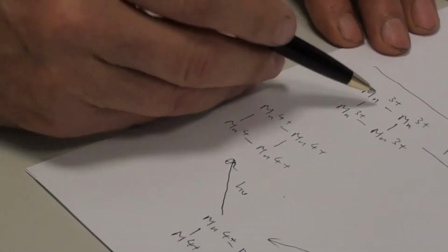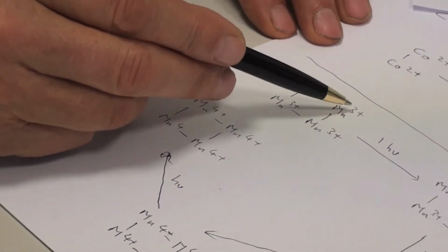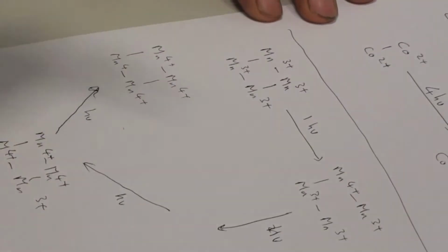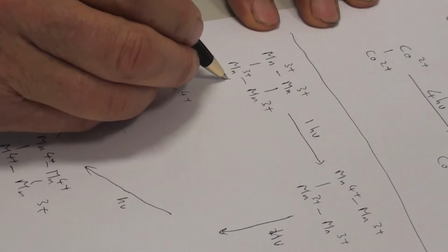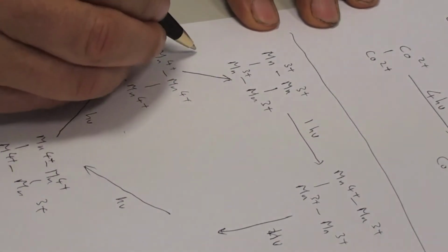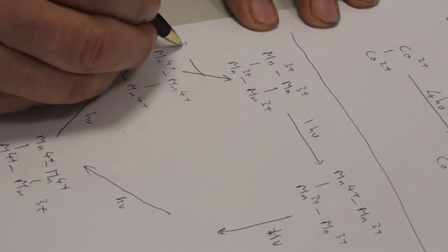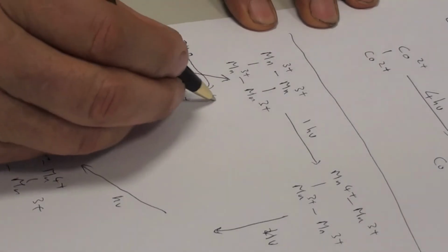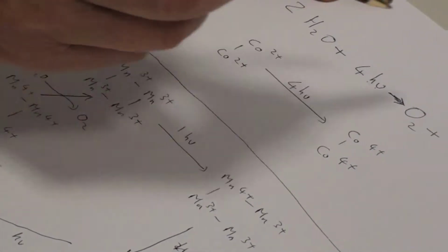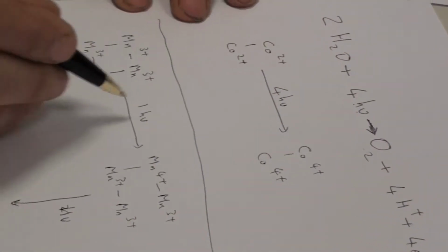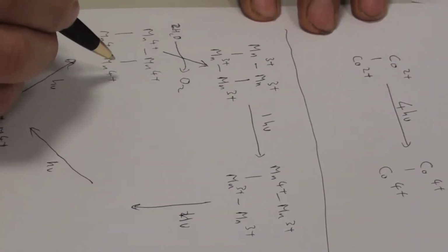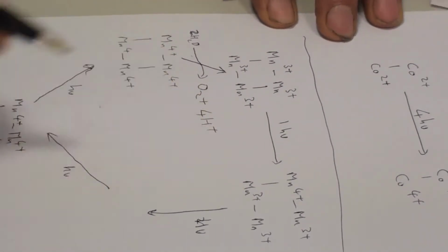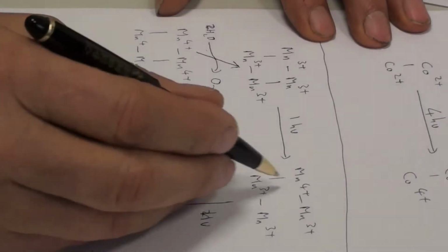Now you've accumulated, how many pluses were there? There were 12 pluses there, now there's 16 pluses. So you've accumulated 4 pluses, 4 oxidizing equivalents, we would say. And at that stage, the 2 water molecules are, in chemical terms we say, oxidized, and an oxygen molecule is released. So it goes back to our equation here, that 1 oxygen needed. So 4 electrons have been taken out of this manganese cluster, and 2 water molecules and 4 protons are released. Not quite like that. Protons are released to go around, and obviously I've left that one out there.